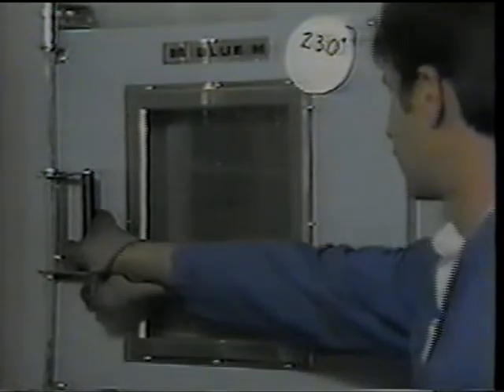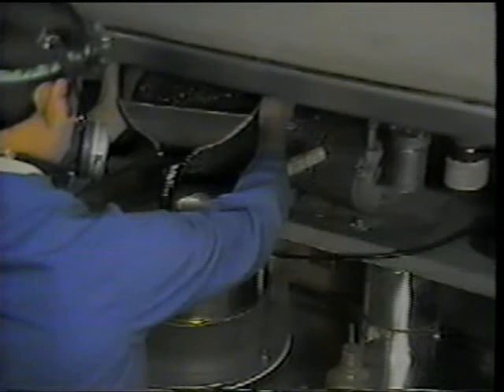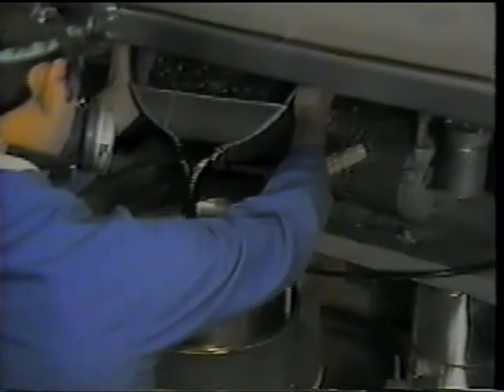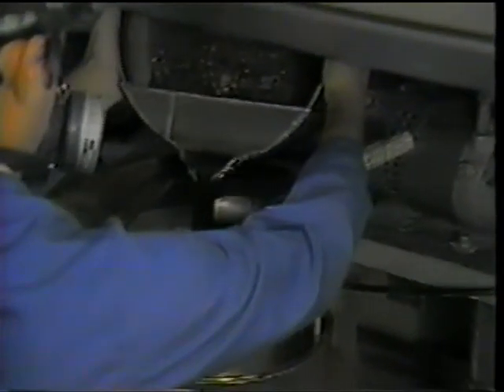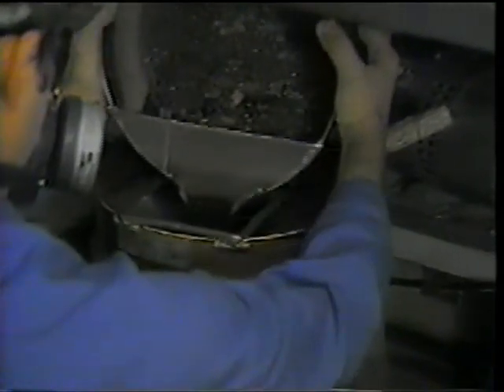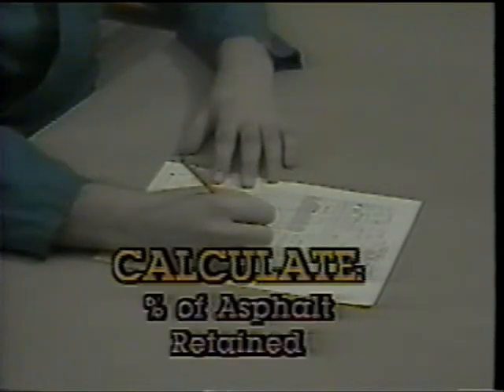Next, place the mixed sample in the oven at 230 degrees Fahrenheit and let it cure for 2 hours. After 2 hours, remove the cured sample from the oven and let it cool for about 15 to 20 minutes. Conduct an extraction test on the cured sample and determine the percentage of asphalt extracted. The percentage of asphalt retained is simply the difference between the percentage originally added and the percent extracted.